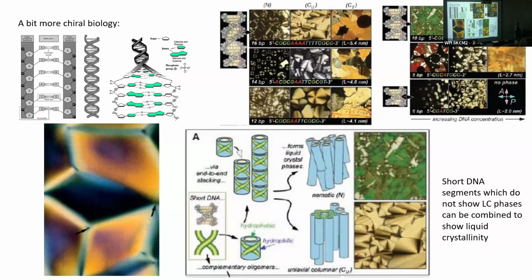And these lines are due to the cholesteric helix. Because whenever your optic axis, whenever your molecules point along the direction of light propagation, there's no birefringence, it will be dark. And it's doing this, it will be dark, and doing that, and so on. So the distance between two of these lines will actually give you the pitch of your helix.